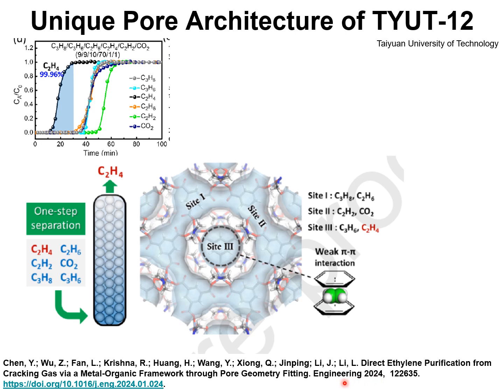The important feature of this metal organic framework is that precise regulation of interlayer pore segmentation allows segmented channels between layers that are decorated with functional groups. There are three types of sites. Site 1 selectively absorbs the saturated propane and ethane.